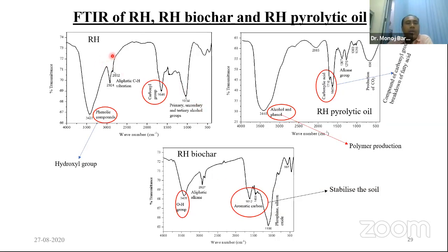This is the FTIR spectra for a sample, that is rice husk, both the biomass and its products, liquid product and solid products. So here you can see this is the FTIR spectra of the biomass of the rice husk. Say, we find a very sharp peak in this wave number area, that is about 3,400. And from our literature survey, we know that whenever some peaks are found in this wave number, it gives an idea of the presence of hydroxyl group, such as phenolic or maybe alcohol.